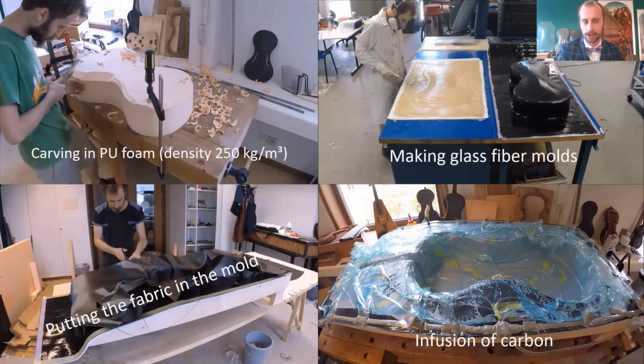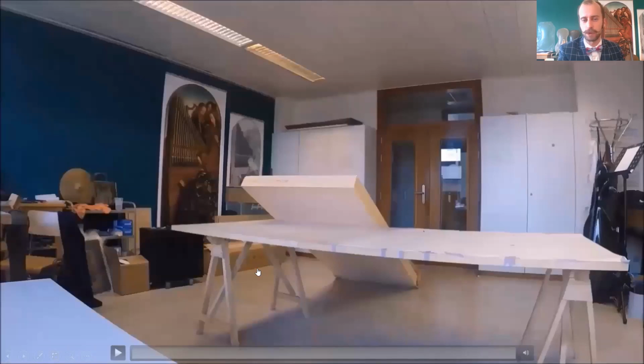So I put the fabric here inside the mold. So this is carbon fiber fabric, just a loose one. It goes under vacuum. And then under vacuum, the resin infuses the fabric, and then it hardens. And when it comes out, it is a solid material. So I will show you here the video. It's about 5 minutes. And it will show the complete making of a cello from carbon fiber.